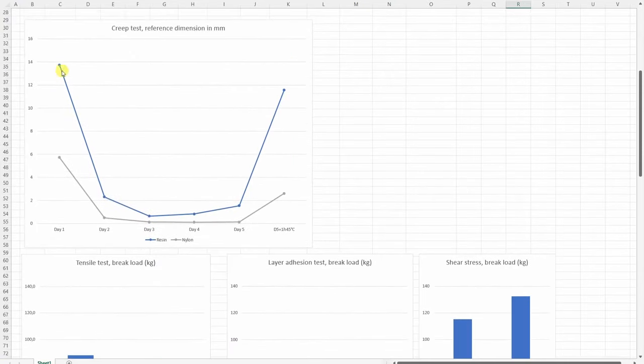So as you can see, with the creeping, the nylon is better, and it almost completely stopped with the creeping after maybe 3rd day. And it had some additional creeping, interesting, on 45 degrees Celsius. The resin continuously creeped even after 5th day. I noticed some deformation, and don't forget here it basically deformed completely on 45 degrees Celsius after maybe 15 minutes.